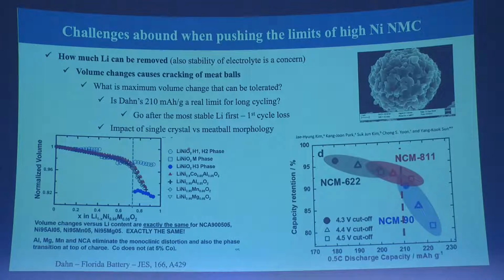And the major problem really is when you push them to the limit. I said we're intercalating in these materials. But as you intercalate, clearly the lattice is expanding. You're putting something in there. So the lattice expands, and if we've got one crystallite this way, the next one this way, as they expand, eventually the interfaces crack. And then that cracks the meatballs. We've got fresh surface in there, which then reacts with the electrolyte, making them more resistive.